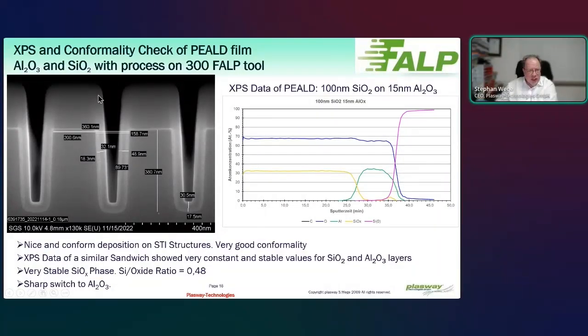So first of all, you see here an ALD composition of aluminum oxide and silicon oxide. And what you see is the nice conformality of this ALD deposition. So it works very nicely also on these STI structures. But what is maybe also very interesting is this XPS data to look at the stoichiometry over a 100 nanometer silicon oxide film and 15 nanometer aluminum oxide film. And if you look, for example, here in the area where we have the silicon oxide and compare the SiOx with the oxygen ratio, it is just flat.